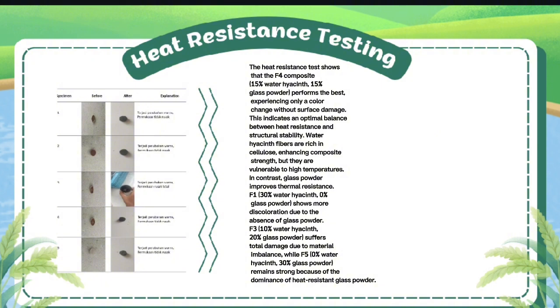Water hyacinth fibers are rich in cellulose, enhancing composite strength, but they are vulnerable to high temperature. In contrast, glass powder improves the thermal resistance. F1, which is 30% water hyacinth and 0% glass powder, shows more discoloration due to the absence of glass powder. F3, which is 10% water hyacinth and 20% glass powder, suffers total damage due to the material imbalance, while F5, which is 0% water hyacinth and 30% glass powder, remains strong because of the dominance of the heat-resistant glass powder.